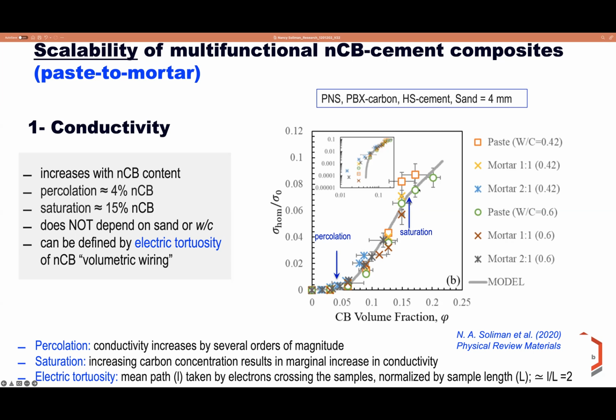which concludes that the conductivity isn't affected by water-cement ratio or sand content. The main parameter that affects conductivity here is the carbon black volume fraction. And also what appears here is that the electrical conductivity versus nanocarbon black volume fraction follows the typical feature of percolation phenomena. This can be illustrated as the 4%.